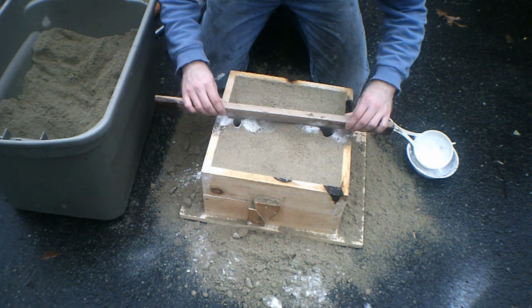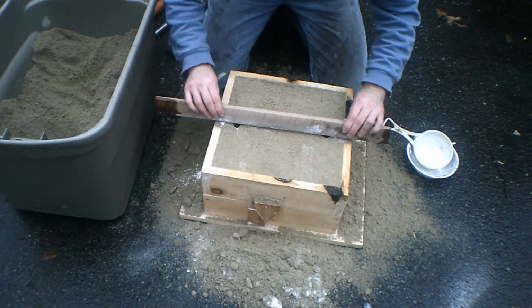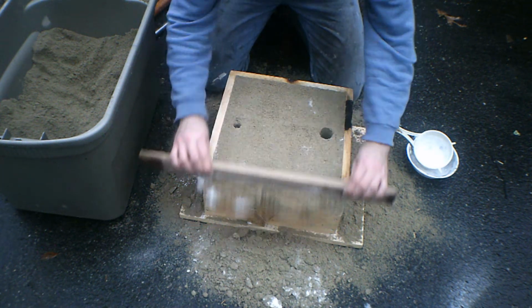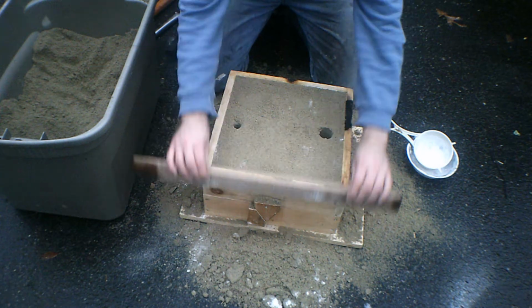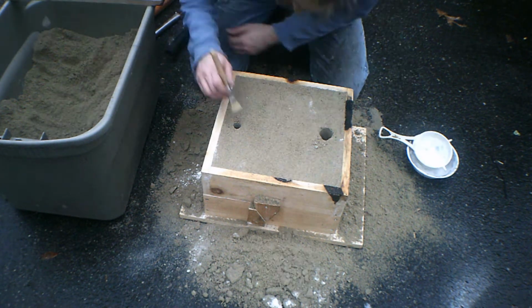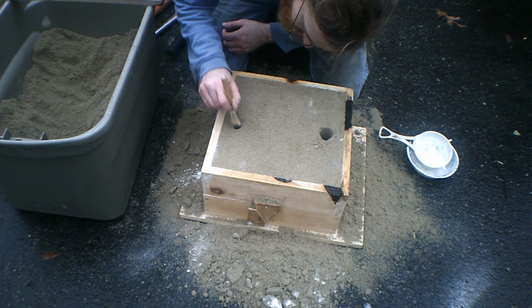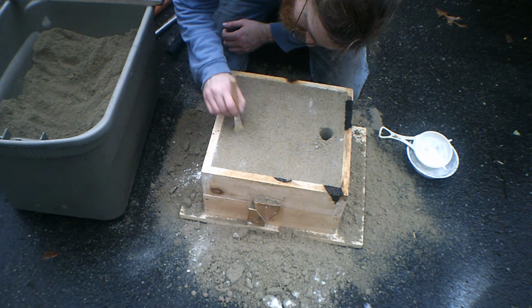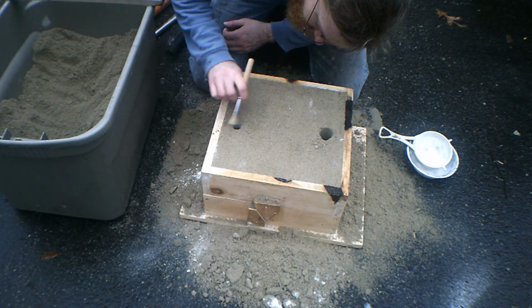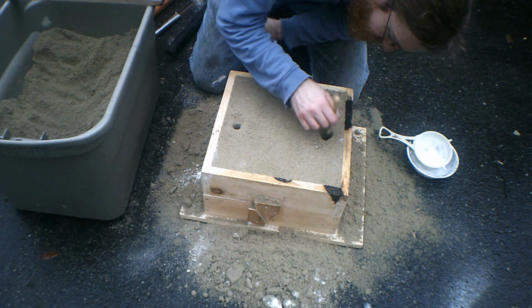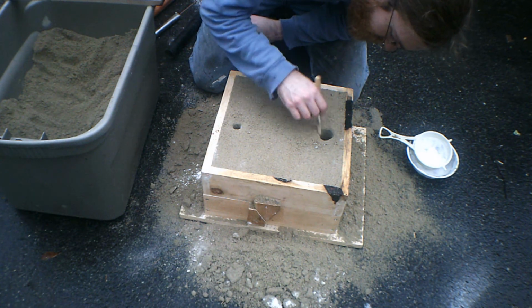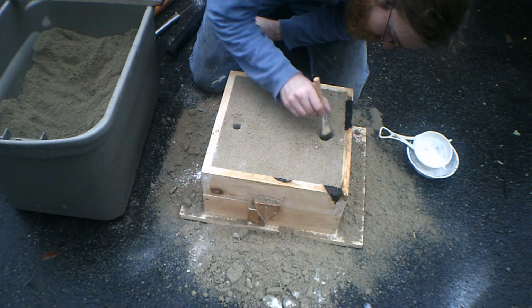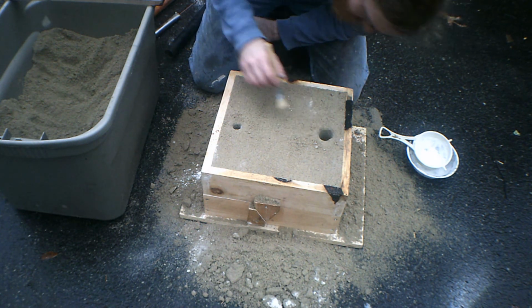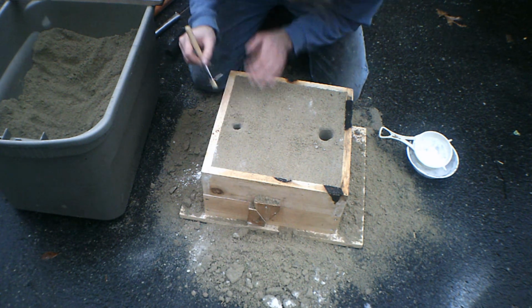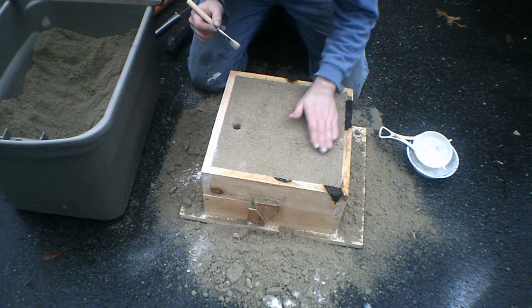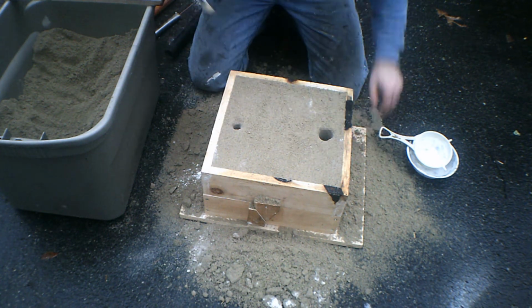Once again, striking off, this time going across the midline of the holes to mitigate as much of the sand going in as possible. And then back and forth a few times to get a truly flat surface. Using a small brush to round the edges makes it so that sand won't fall in from those sharp corners. Sharp corners are inherently weak no matter what you're designing, and sand is certainly no exception. That just puts a slight radius on them and makes everything go a lot smoother.